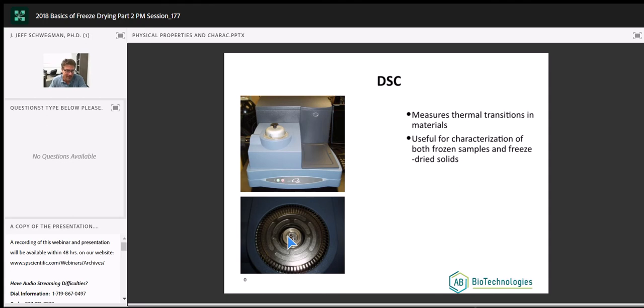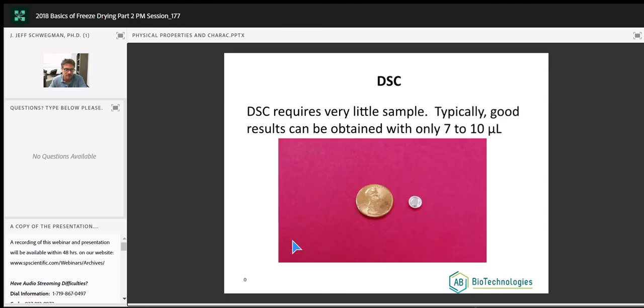The reference pan sits in the back. It's got a little pedestal. The sample pan sits in the front on its own little pedestal. We've used very small volumes. We've got 7 to 10 microliters here. I'm using more like 18 these days, 18 microliters, just for the simple fact that the sensitivity of the instrument does depend on the amount of sample we put in. We don't want to overload it, but especially for some low energy events that we might see, which we'll talk about. So 18 is about what we're using these days, 18 to 20.